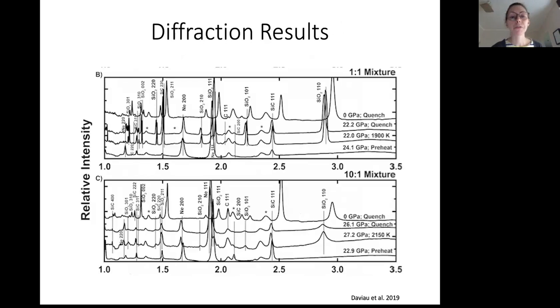Here are the diffraction results, which actually showed up kind of grainy, from two of the mixtures, the 1-to-1 mixture and the 10-to-1 mixture. Looking at the 1-to-1 mixture, d-spacing is on the bottom axis. I think the label got cut off. The bottom pattern is the preheat pattern, where you can clearly see silicon carbide diffraction and neon diffraction, and you don't see silica yet because we loaded an amorphous silica sample. The silica comes up after the sample heats, and now you start to see these stishovite peaks, which is the high pressure form of silica.